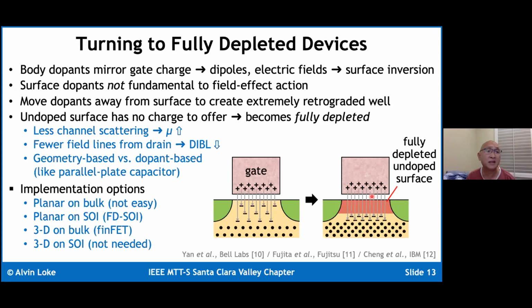There are multiple ways of implementing a fully depleted device. You can build planar on bulk, which is what's drawn here, but it's actually very difficult to do, because to do planar on bulk requires you to epitaxially grow an undoped region of silicon on top of a heavily doped region of silicon. And that's very difficult to do because epitaxy is a very high temperature step during which the fast diffusion of dopants from underneath will rush upwards to basically dope the undoped layer that you're trying to keep undoped. So it's generally very difficult.